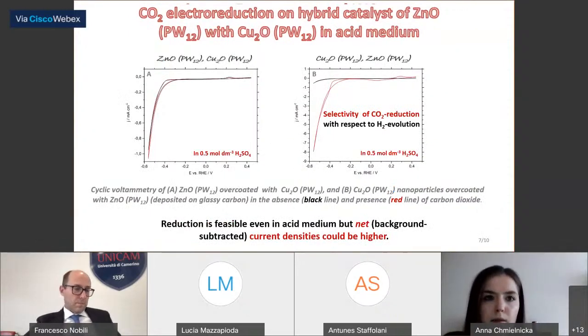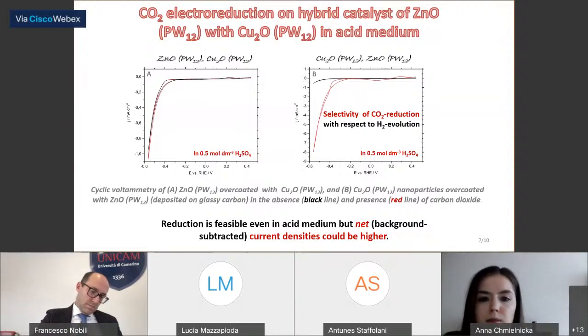On this slide, we have CO2 electroreduction on a hybrid catalyst of modified zinc oxide with modified copper-1 oxide. Figure B shows selectivity of CO2 reduction with respect to hydrogen evolution. In both graphs, we can see typical reducing copper-1 oxide peaks, and in both cases, reduction is feasible, but net current densities could be higher.